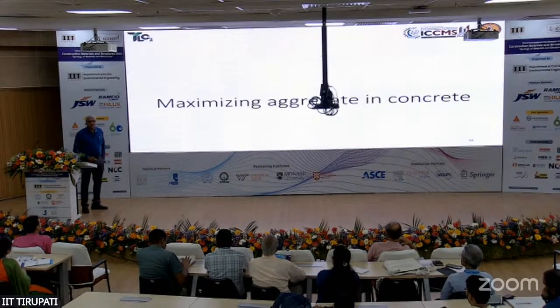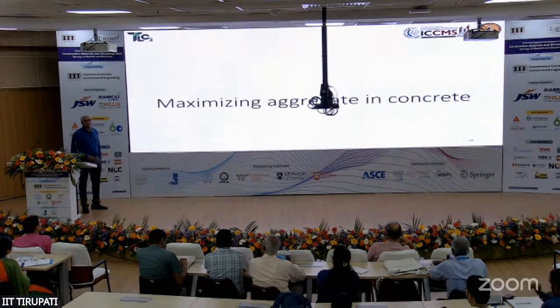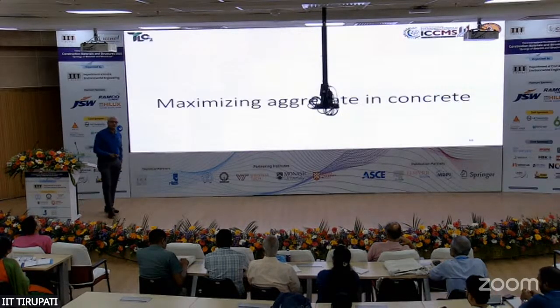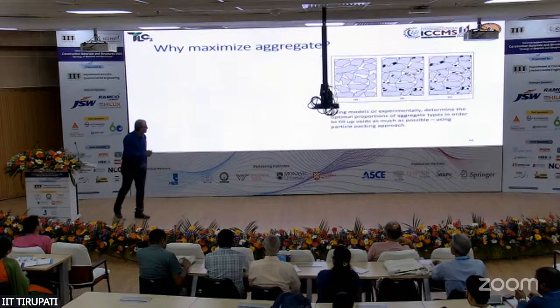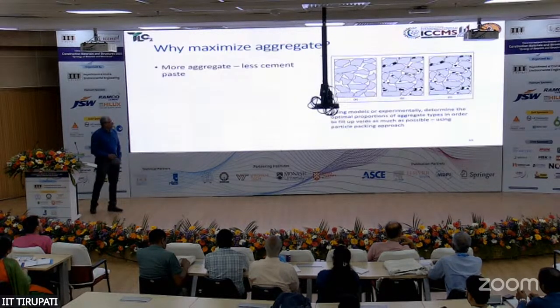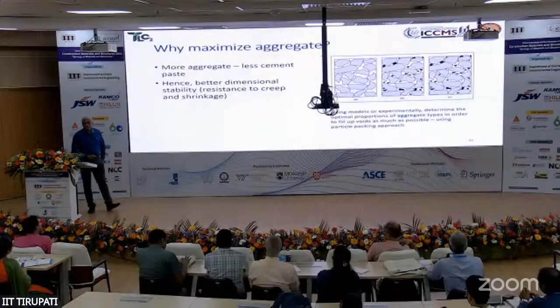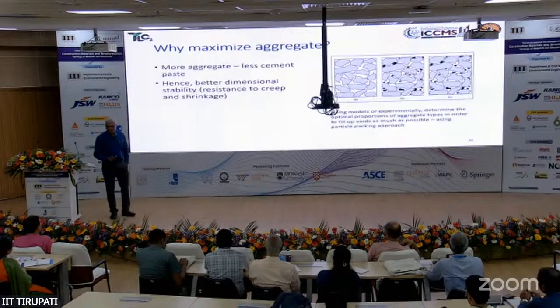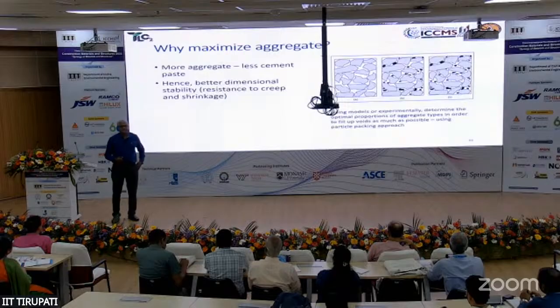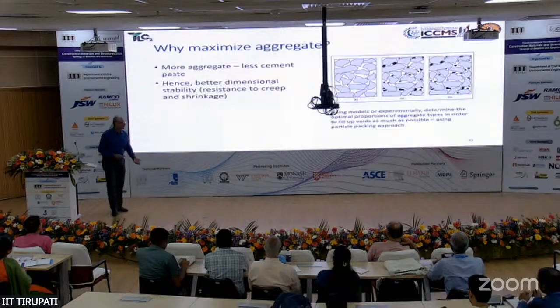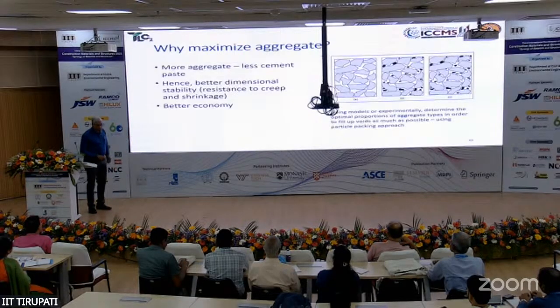Maximizing aggregate in concrete obviously is very important from the point of view of reducing cement, and that automatically reduces your CO2 impact, right? How do you maximize aggregate? One strategy could be particle packing. This is a concept that we borrowed from the powder metallurgy industry, where they look at particle distributions and then optimize them so that the material can get the best solid packing without much voids in the system. So particle packing is an approach which could be followed.